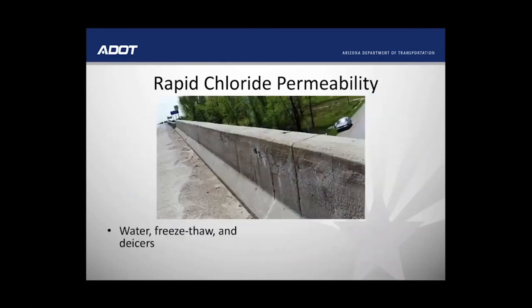The second, not only is the integrity of the surfaces compromised, but the capillaries provide a clear path for water and salts to penetrate the concrete. Third, the concrete simply is not as dense, so it is therefore more permeable without inclusion of the silica fume. So if we are not in the very low range, 1,000 coulombs or less, then these damaging effects are more likely to occur. We can have leaching of the calcium hydroxide from the paste, decalcification of calcium silicate hydrate, those are the CSH bonds that provide strength, conversion of CSH to magnesium silicate hydrate, or MSH, formation of salt crystals, formation of oxychlorides, acceleration of alkali silica reaction, ASR, and alkali carbonate reaction, ACR, and also corrosion of the reinforcing steel.